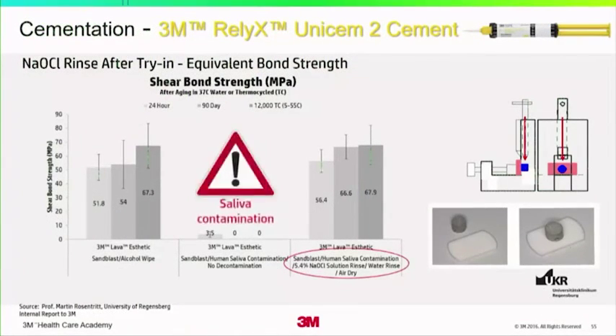The one thing I would tell you is that saliva contamination is a factor, so please make sure that the saliva is removed and dissolved by using sodium hypochlorite, or, as I mentioned earlier, you could use a cleaning agent to decontaminate the restoration, rinse and dry it, and you're ready to go.